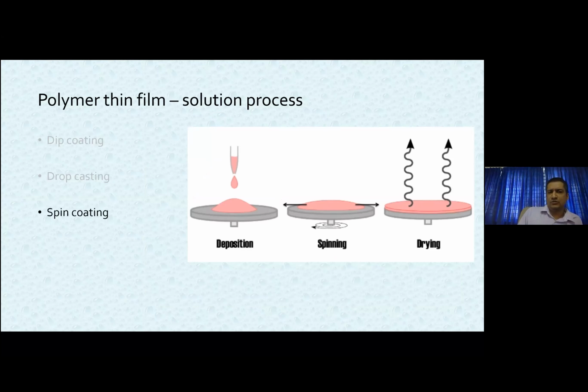Moving to the next approach, something called spin coating, which is more or less the most preferred method on laboratory scale for one particular reason: it gives uniform film thickness over the surface on which you do the spin coating. Here the parameters that should be carefully controlled are the rate at which you spin, the time for which you spin, the concentration of the solution you use, and the interaction between the solvent and the substrate. You can have a hydrophobic or hydrophilic substrate. Suppose you have a hydrophobic substrate and try to coat with a hydrophilic solution, then nothing will stick onto the coat, and vice versa. So you have to play with the surface and the solvent system to get uniform coating.